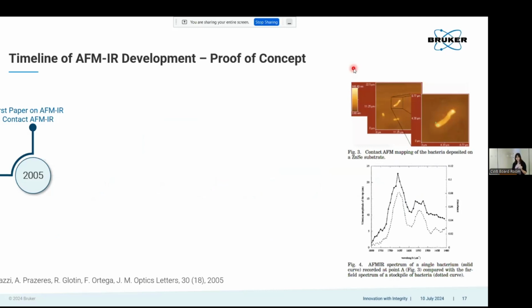So we're looking at this individual bacteria on the surface again. It is about a few microns long in this case. You can put your probe on the spot, and then you can measure that infrared spectrum. This black, more solid line up here is the measurement that Alex took using this innovative technique. And this dotted line beneath is what they measured through FTIR. So again, you're seeing this direct relationship between the magnitude that you're measuring through AFM-IR and FTIR in 2005, 19 years ago.